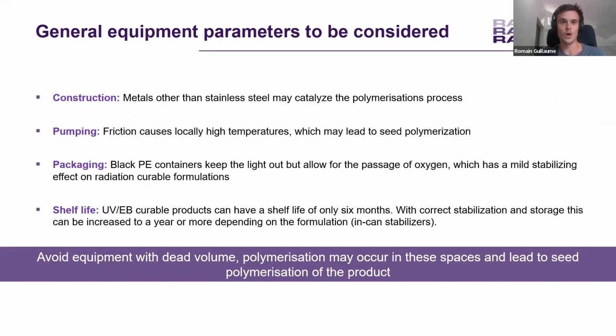Let's jump to some facts about general equipment parameters that we have to consider for the formulation, for the chemistry itself. About the construction, metals other than stainless steel may catalyze the polymerization process. About the pumping, some friction causes locally high temperatures, which may seed some areas with polymerization of the formulation itself. The packaging is also very important to consider. Black PE containers keep the light out, but also allow the passage of oxygen. And we know that oxygen has a mild stabilizing effect on radiation curable formulations.